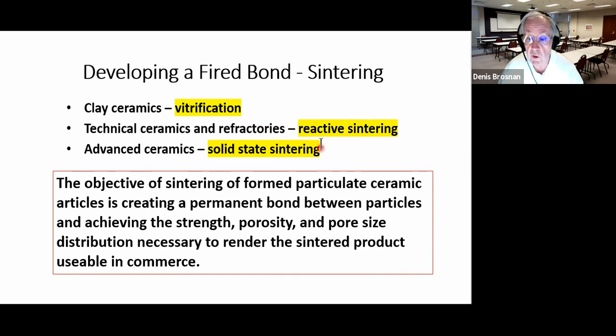In advanced ceramics, we typically would like to be as small in porosity as we can be, below 1%, perhaps below 0.5%, to achieve the maximum possible strength at room temperature and at elevated temperature. But basically, there are three types of fired bonds that can be formed depending on the chemistry of your system. The chemical analysis for clay ceramics tends to favor vitrification because of the lower melting points of the liquids. These melting points are typically just below red heat, and we can start forming melted phases within the ceramic then.